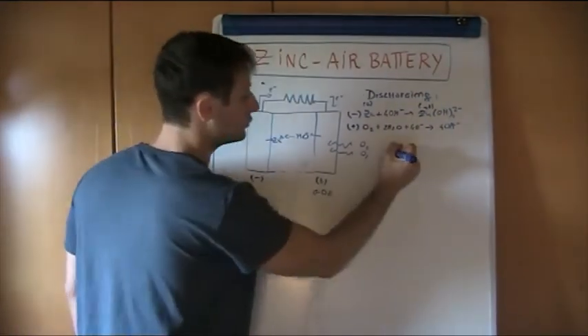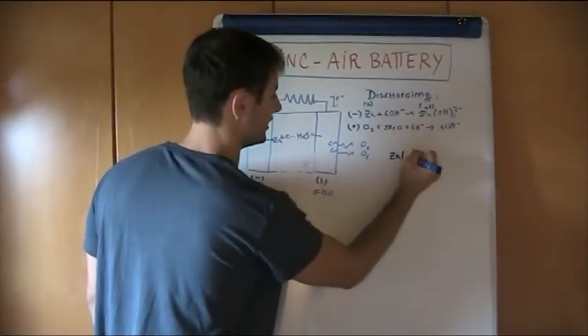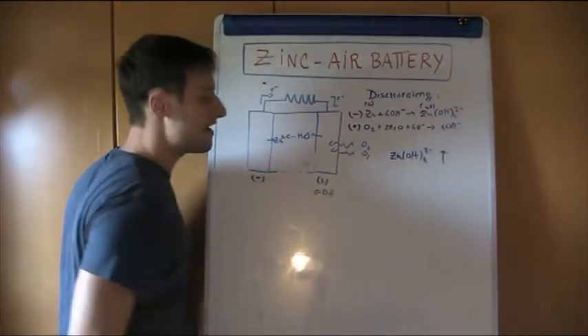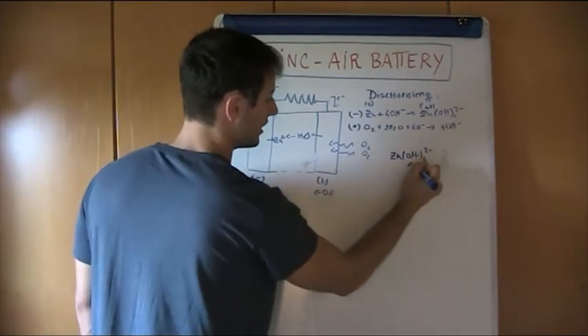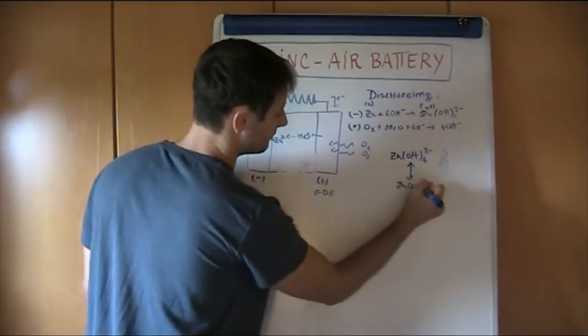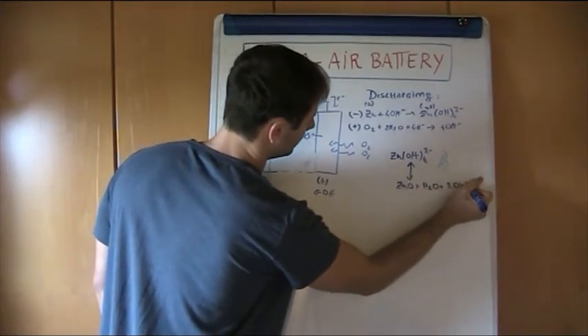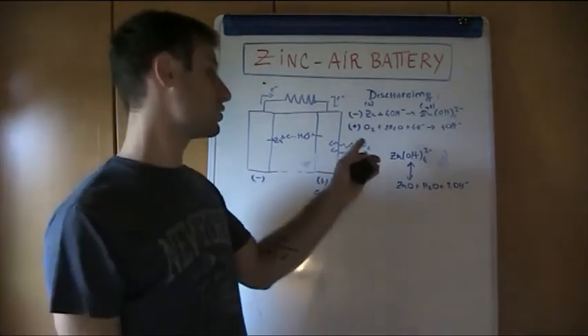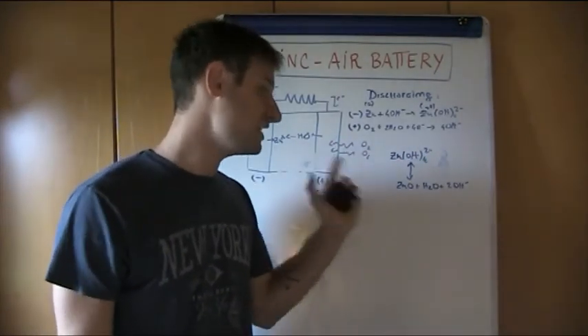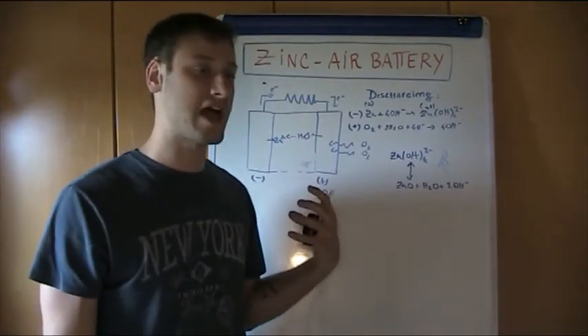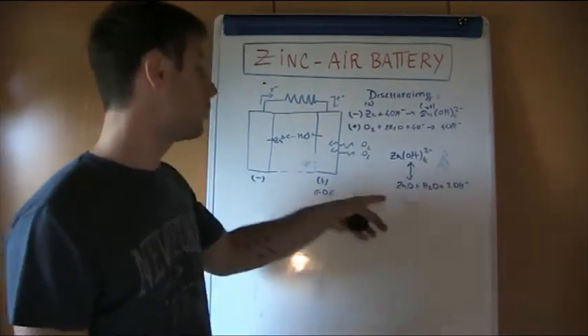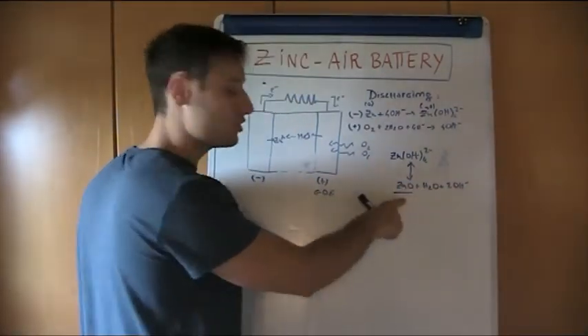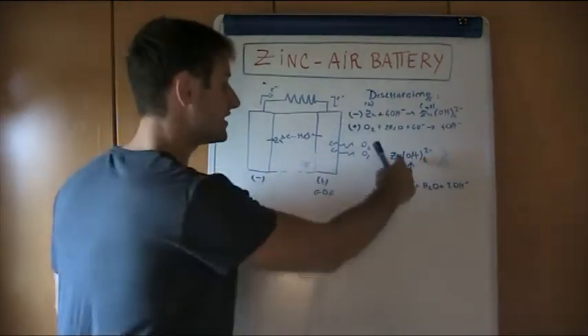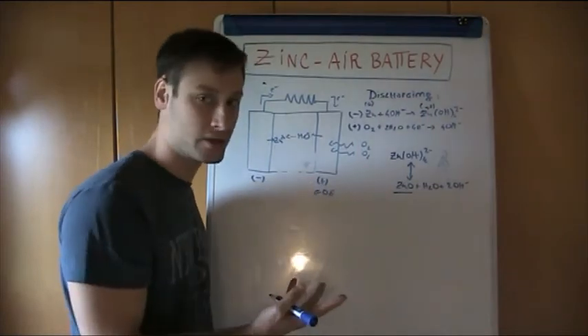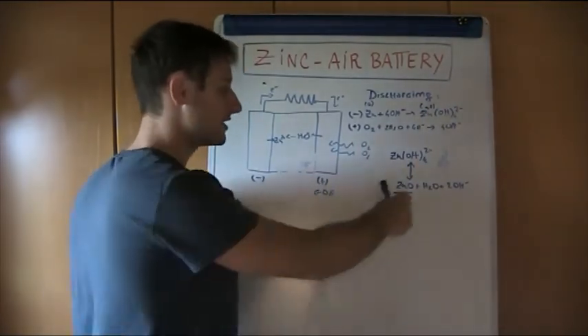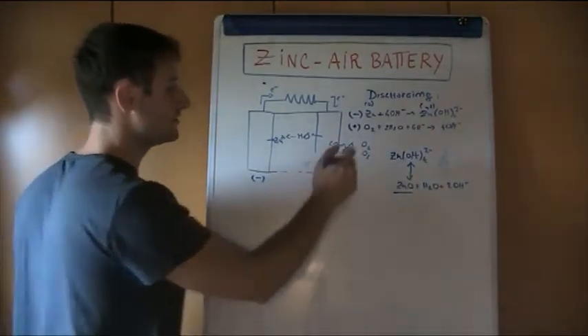But when the amount of dissolved zinc in the form of zincate is very high, we have an equilibrium between this species and the formation of zinc oxide plus water plus 2OH minus. So basically what's happened is that when the concentration of dissolved zinc in the form of zincate is huge, because the reaction is proceeding by a lot, for instance, we can have the formation of an insoluble species, zinc oxide, as a solid. The zincate is soluble, it is not a solid, whereas the zinc oxide is a real solid, plus water and this. So this is important in the electrolyte.